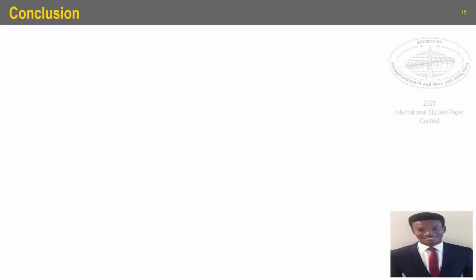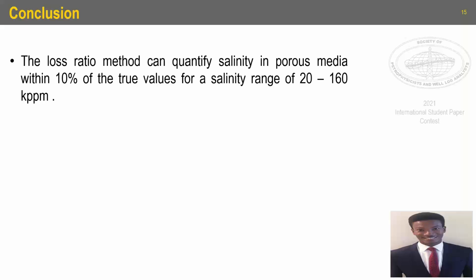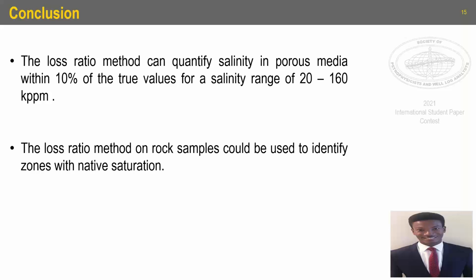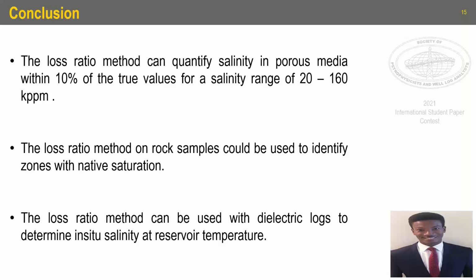We've been able to see that the loss ratio method can quantify salinity in porous media within 10% of the true values for a salinity range of 20 to 160,000 ppm. We also see that the loss ratio method can be used on rock samples to identify zones of native saturation. Based on this, we can then use this method in combination with our dielectric logs to determine in situ salinity at reservoir temperature.